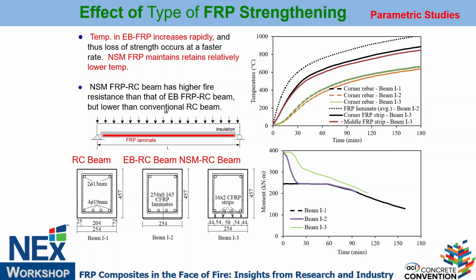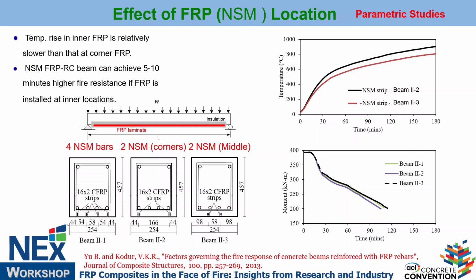Now if you add NSM, as you can see here, though NSM temperatures are rising, they are rising slowly, and after glass transition temperature it drops, but still it continues to have some strength because of the protection it gets from the concrete cover thickness, right? Gradually it drops. Now if you see, for example, this one here, how to strategize even putting this NSM. If you want to use NSM as the reinforcement, this is not a good option to put NSM across, putting a number of bars. Because the heat will be coming at the corners from both sides. So in a fire situation, corner bars will lose strength very quickly, right?